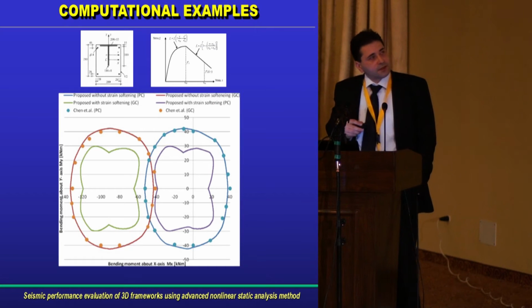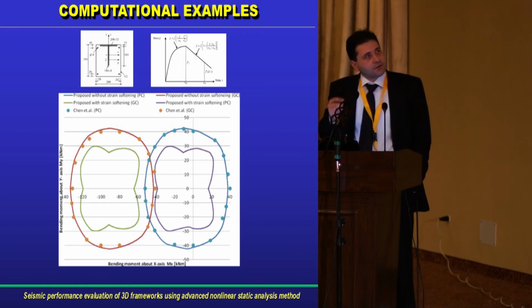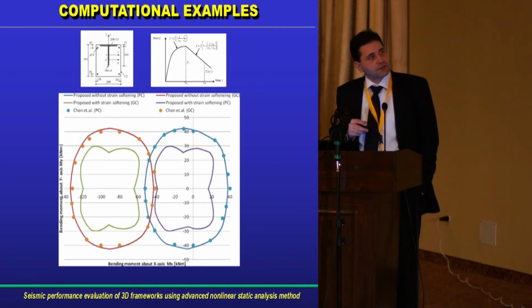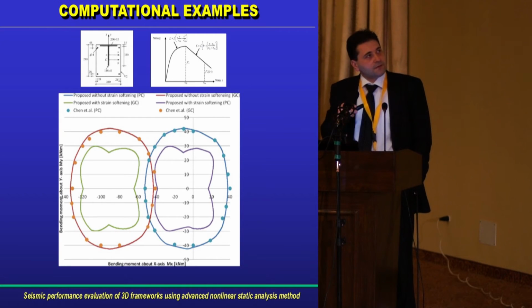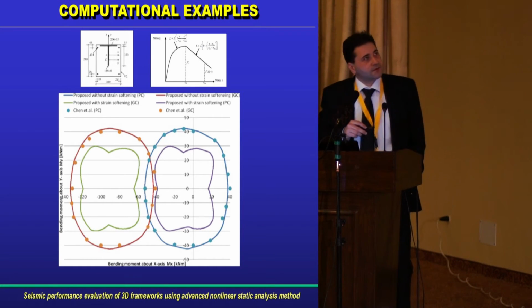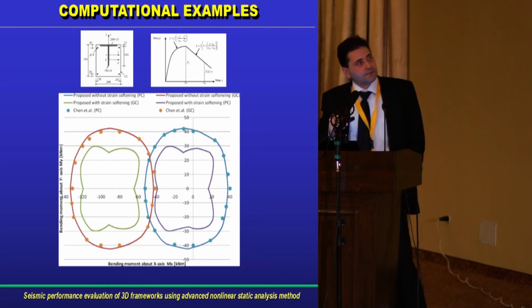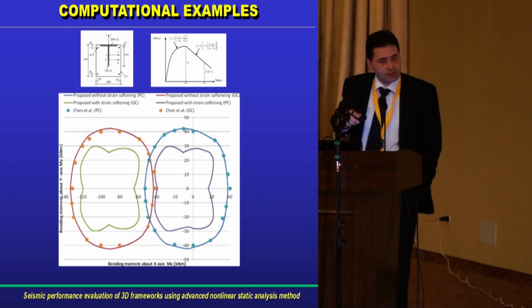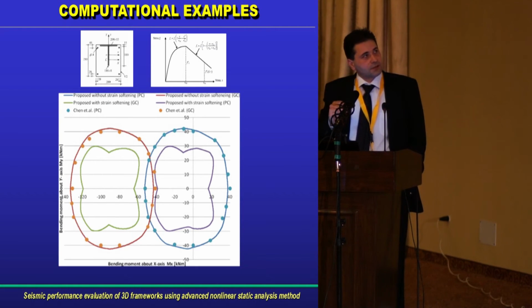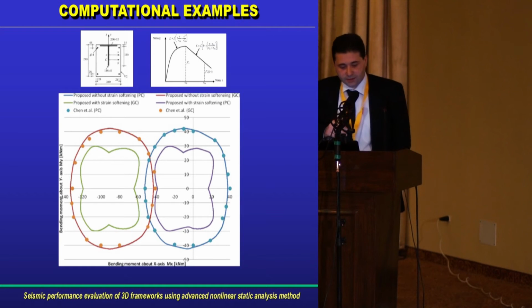In this figure are represented the moment capacity diagrams for axial force. In this example, the axial force is 3,000 kilonewtons. We can see that if we consider the strain softening effect, the descending branch of this curve, the ultimate strain capacity is reduced, and also the capacity interaction diagrams, the moment capacity diagrams, are non-convex. In the literature, all these interaction diagrams are considered convex, but usually they consider the plateau, they don't consider the strain softening effect.